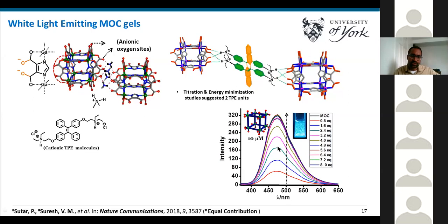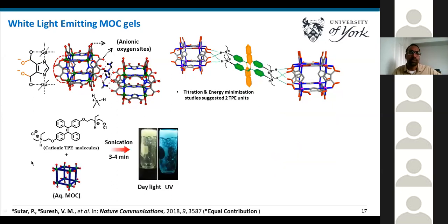From the titration analysis and energy minimization studies, we found that two tetraphenylethene cationic molecules can fit in between two metal organic cages via charge-assisted hydrogen bonding interactions between the metal organic cage and the cationic TPE. With this data, we proceeded to create fluorescent hydrogels. When we mix this cationic TPE with the aqueous metal organic cage, just by sonication within 3 to 4 minutes, we see a stable gel formation.